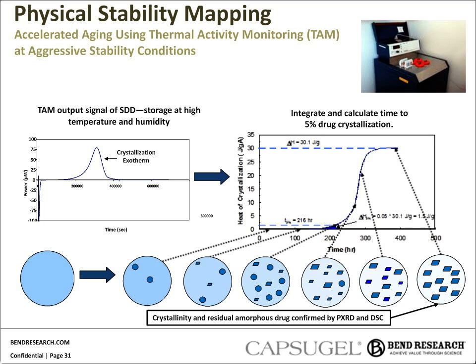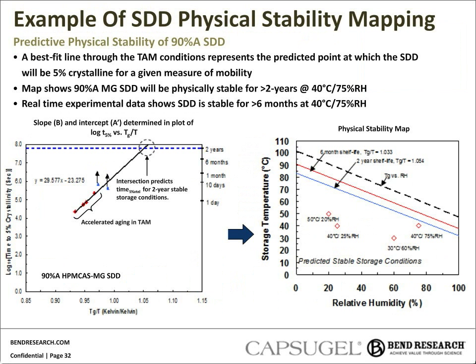And the cartoon here describes how that crystallization exotherm is then translated into the integral of that. And what we'll do with this in terms of modeling is we'll look at the integration of that crystallization heat flow signal, and based on what we can typically robustly quantify in, say, a powder X-ray experiment, which is about 5% crystallinity. So we'll map out the time it takes to generate 5% crystalline material, and then plot that against different storage conditions to generate a physical stability map. So on this slide, we're showing that in the bottom plot on the bottom left. We're looking at the log of the time to 5% crystallization versus the TG over T, Kelvin to Kelvin.